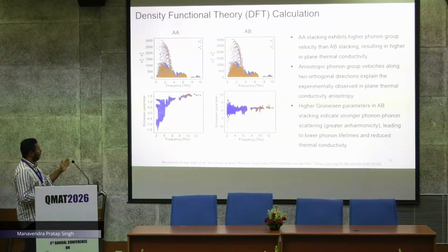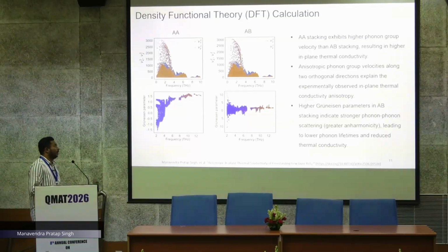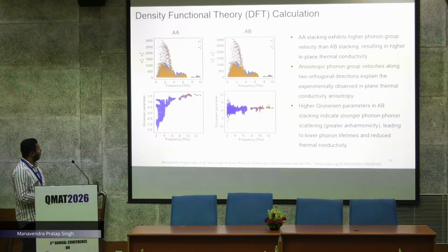So AA has more thermal conductivity and AB has less thermal conductivity, and here we can see the phonon lifetime, which we can relate with the Gruneisen parameters. So AB stacking indicates more phonon scattering, so greater anharmonicity, leading to lower phonon lifetime and reduced thermal conductivity. So this calculation supports our experimental findings.